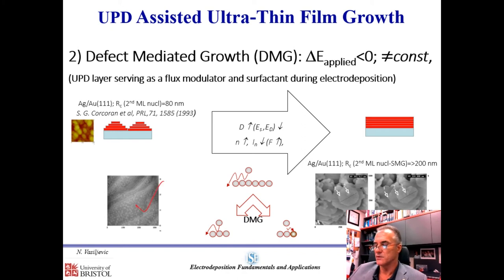That enhances the nucleation, which is good because it improves the situation where the clusters become smaller and the step-down process is facilitated. But it also does all the things that surfactant growth already does. Basically, you can see here the clusters; we observe that the size of the clusters on which the nucleation on top starts to happen is actually much bigger. And that's one of the indications that we are mitigating the barrier for the step-down process.